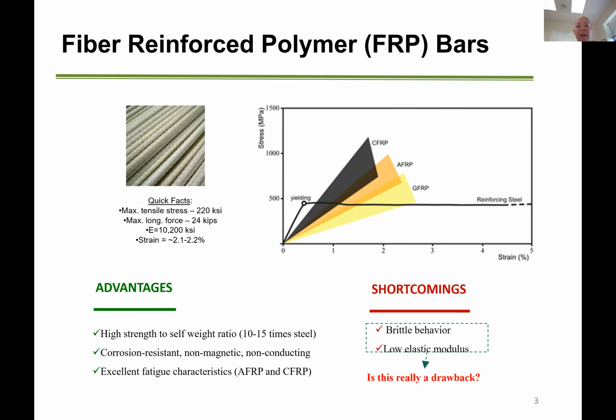So backing up, for the bridge decks, we realized that these FRP bars in general had several advantages. The high strength to self-weight ratio is about 10 to 15 times that of steel. These bars, because they're composite, are corrosion resistant, non-magnetic, and non-conducting. And particularly we've seen with the AFRP bars and the CFRP bars, the carbon, we're noting excellent fatigue characteristics.